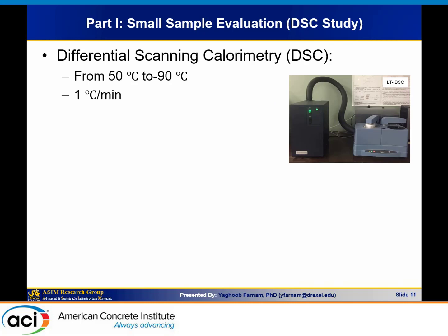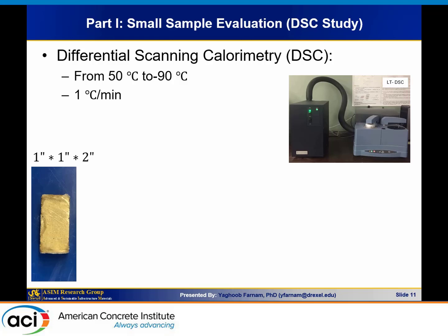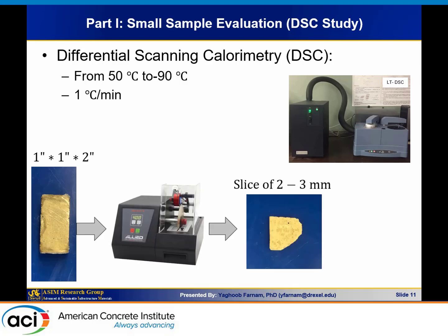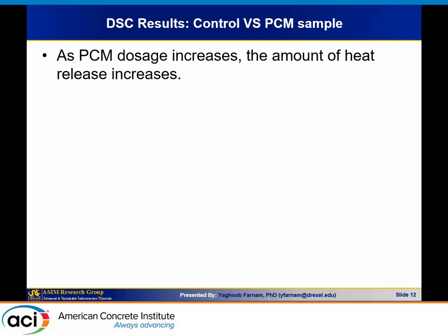So this is a picture of the differential scanning calorimetry device, and normally this is a very sensitive device for small samples. You have to put something like 5 to 20 milligrams of sample. So we made our sample, and then we used a diamond saw to cut slices out of that, 2 to 3 millimeters thick, and then we took a little bit of that, 15 to 20 milligrams, a very tiny sample. And then we put it inside the differential scanning calorimeter and looked at the temperature profile of that.